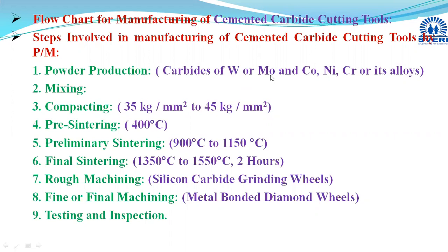Molybdenum powder particles are obtained from molybdenum oxide, and they are reduced by the chemical reduction process with the help of hydrogen. Then cobalt powder is also obtained, as is chromium powder. These also can be obtained by reduction of their respective oxides, and this reduction is done by using carbon or hydrogen. In this way, by using suitable chemical processes, these powder particles are produced or manufactured, and that will be the first stage of manufacturing of cemented carbide cutting tool.